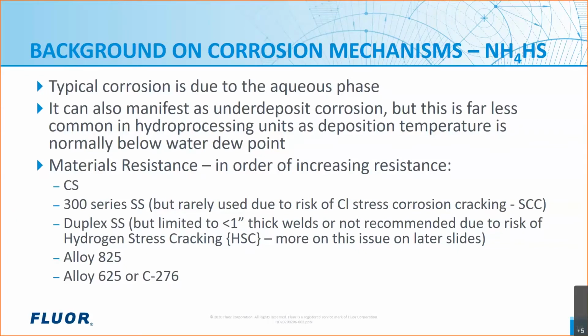So now one of the most common upgrades when you think carbon steel is going to corrode is alloy 825. And if it's in very severe conditions, you might go to alloy 625 or Hastelloy C276. And even going from carbon steel to 825 is a major increase in cost. Just material costs are probably 5 times higher.